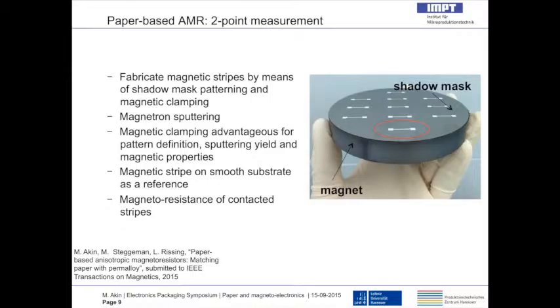So, when combining magnetron sputtering and a magnetic clamping, one might think, well, this might not work. But what we found out is basically in our setting, in our machine, the magnetic clamping was advantageous because we obtained a good pattern definition, we obtained a higher sputtering yield, and the magnetic properties of the coating as sputtered were much better than when sputtered on a non-magnetic pellet. The magnetic stripes, we manufacture those also on a smooth surface, which we use as a reference, and the smooth substrate is the fused silica material we used in the first experiment.